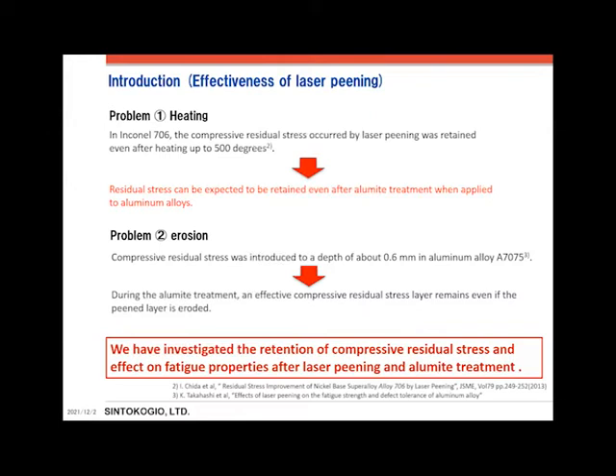Also, it has been reported that compressive residual stress was introduced to a depth of about 0.6 millimeters in aluminum alloy A7075. During alumite treatment, the effective compressive residual stress layer remains even if the peened layer is eroded. So we have investigated the retention of the compressive residual stress and the effect on fatigue properties after laser peening and alumite treatment.